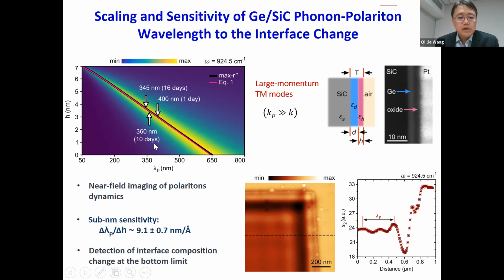And then from the result, we can reveal the sub-nanometer sensitivity of these Phonon-Polariton wavelengths to the change of this oxide layer. So even if the oxide layer thickness changes by just 1 angstrom, the Phonon-Polariton wavelength can change by 9 nanometers, which is observable. So this result really gives us detection of interface composition change at the bottom limit. It also shows the potential of using such a system for the detection of chemical reactions, okay, especially at the interface.